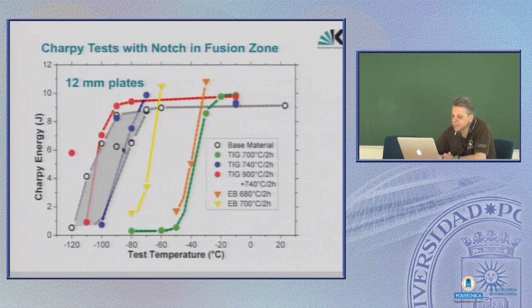Then next would be yellow. That's an electron beam weld again with 700 C. This comes not quite, but near to the baseline base material. And you certainly can't forget this orange and green. Orange is only 680 tempering, and you see this difference of only 20 degrees in tempering has a very big effect in the shift of DBTT. So this is brittle, this is not so brittle.